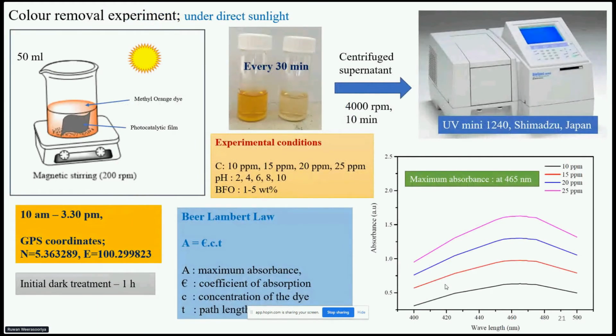After making the photocatalyst, the methyl orange dye was prepared with 4 different concentrations: 10, 15, 20, 25 ppm with 5 different pH values: 2, 4, 6, 8 and 10. After that, the prepared photocatalyst was immersed inside the dye, and initially dark treatment was conducted for 1 hour to achieve the adsorption-desorption equilibrium, and after that irradiation was allowed. The irradiation experiment was conducted from 10 am to 3:30 pm as the maximum irradiation time. During the experiment, every 30 minutes, 5 ml of the dye was taken out and subjected to UV visible spectroscopy analysis after centrifuging at 4000 rpm for 10 minutes.